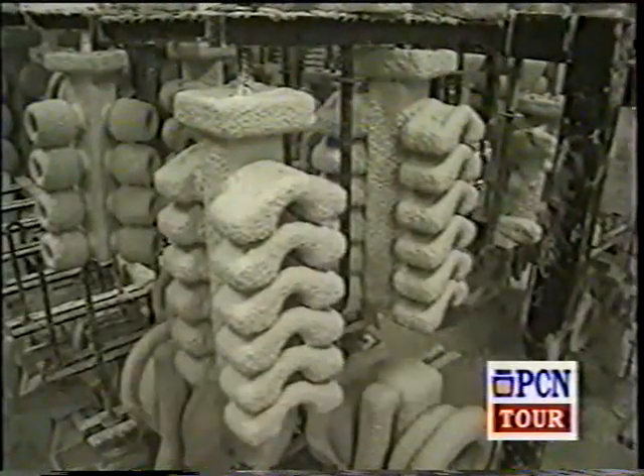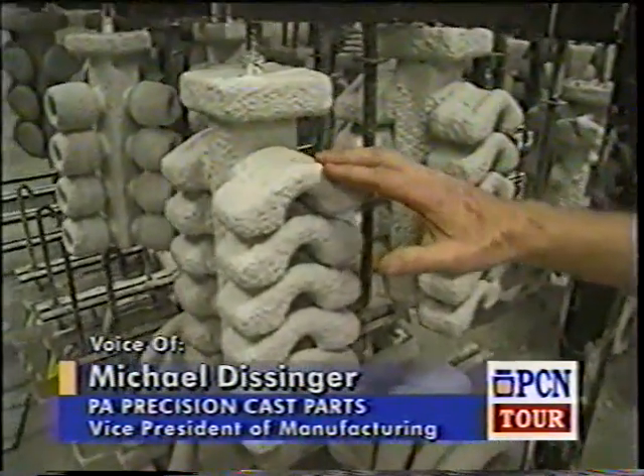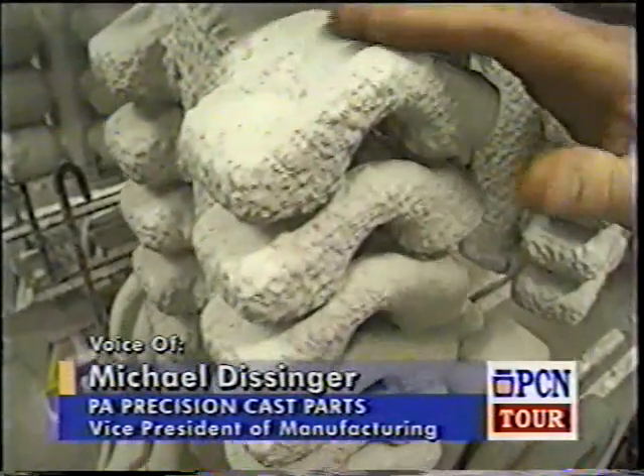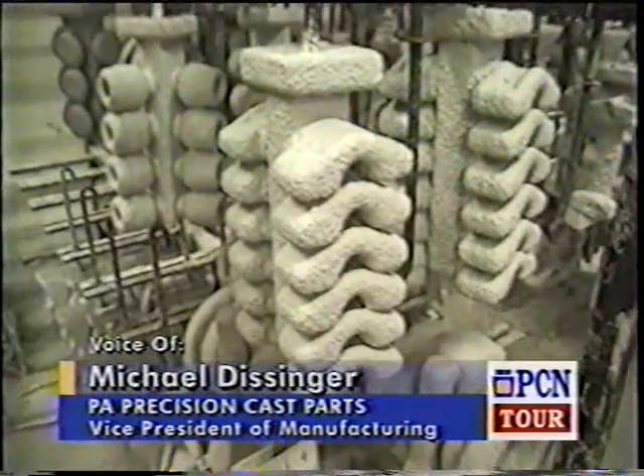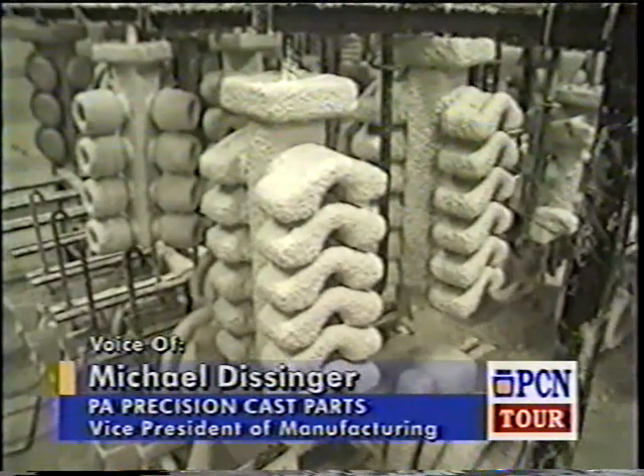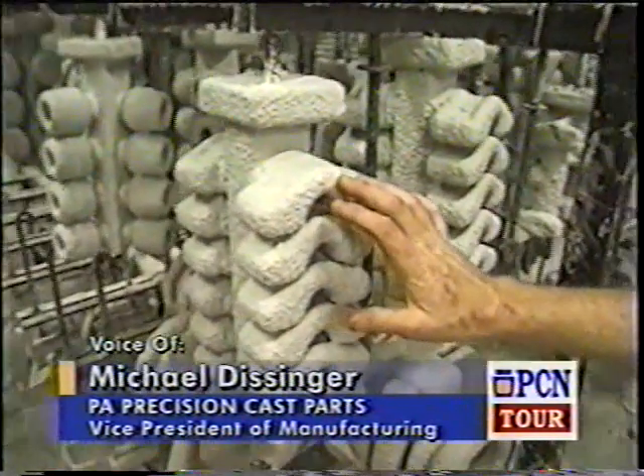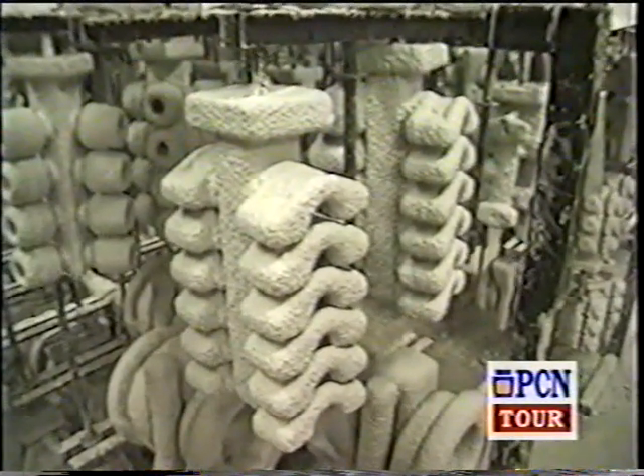What you're seeing now is a mold that has been completed. The final coat was the seal coat in the slurry, but no stucco on top. It holds the whole thing together and gives us a nice smooth texture. These molds need to be completely dry before they can go to the next operation, which is the removal of the wax and styrofoam. Remember, inside this ceramic shell is the styrofoam sprue and the wax pattern. Before the metal can be poured into this mold, it needs to be removed.